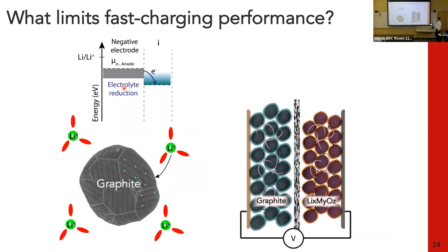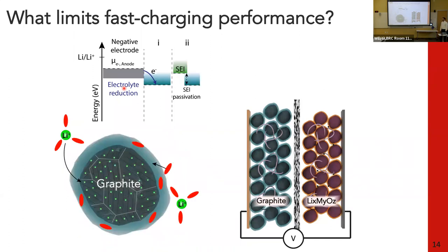Well, during the first charge, what happens is we start putting lithium into this graphite electrode where it really doesn't want to go. The energy level starts going up, right? So on this energy scale over there, it starts going up. And at some point, the electrons inside of this graphite are so unhappy that they can actually jump from the graphite into the electrolyte, decompose the electrolyte, and that forms what we call the solid electrolyte interface, or SEI, this blue ring around the graphite. This SEI is an ionic conductor, but an electronic insulator, so it prevents those electrons from continuing to hop into the electrolyte, and this passivates the surface of the electrode and enables that 1,000 cycle life.